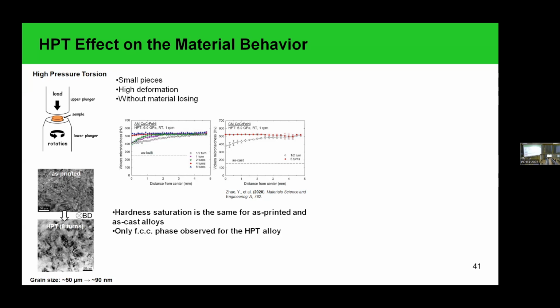So here you see the evolution of the grain size from the as-printed structure. The size of the elongated grains was about 50 microns, and after 8 turns it was about 90 nanometers. And we observed the hardness saturation of these materials as well.